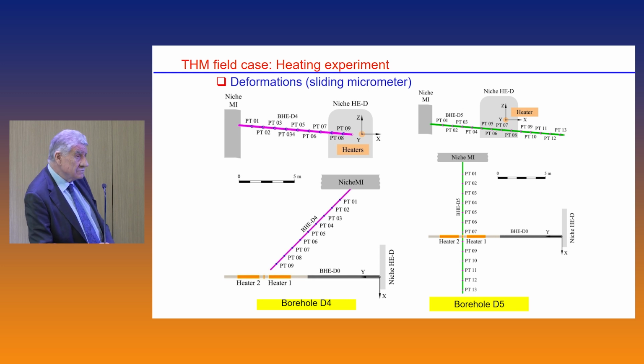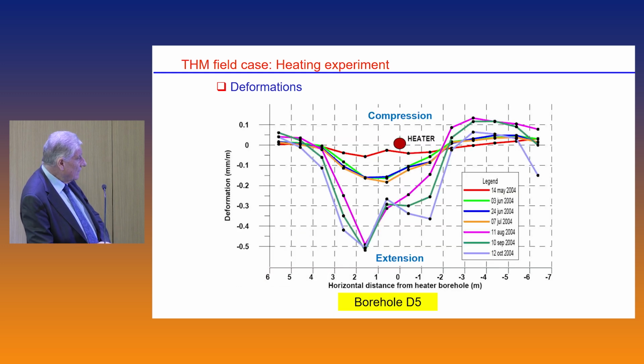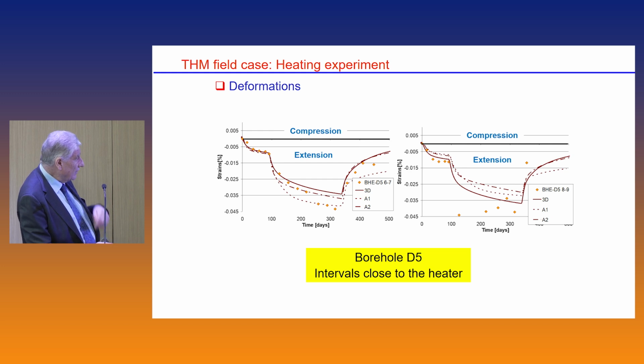We can look at deformations. There were two boreholes with the sliding micrometers, and I'm just going to look at this one, which was going through the central part of the heater, below, as you can see here. This is the heater, below. These are observations at different times, and we can see that here we have extension close to the heater, partially compensated by compression away from the heater, and the comparison with the experimental observations, which are these orange quadrangles, is again picked up throughout by the analysis.